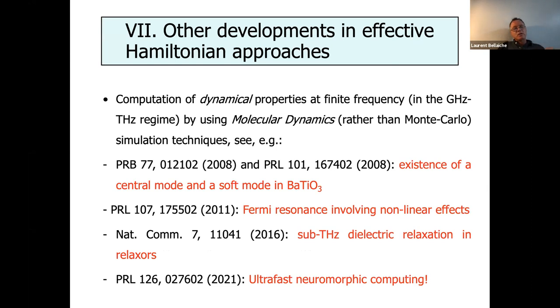For instance, in these two papers of 2008, what we proved using effective Hamiltonian and molecular dynamics, in collaboration with the group of Jirka Linka in the Czech Republic, is that there are two modes that are very important in barium titanate: the soft mode, as is usual, but there is another mode called the central mode, and this is basically characteristic of polarization jumping from plus to minus as a function of time. To understand barium titanate, it is important to have these two modes. There was a controversy: is there only the soft mode or the central mode? These papers, I think, put an end to this controversy. You should deal with two modes.